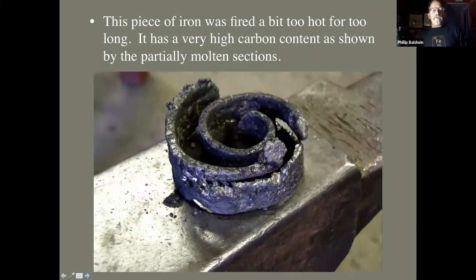And this was a little bit overdone. You can see how it melted, right? The surface turned liquid. I also did not fold and weld this several times to drive out even more slag, so it's very coarse material. But we have very high carbon content. Next slide, please.